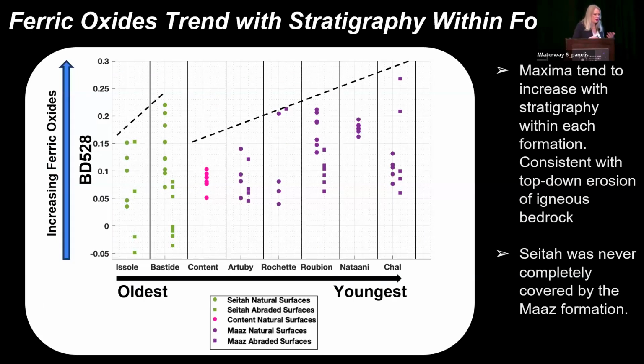So to address the exhumation histories of Jezero Crater, we plotted the BD528 value versus stratigraphy. Stratigraphy is broadly increasing from left to right. Here we see that the maxima increase with stratigraphy within each formation, and that this could be consistent with top-down oxidation of these surfaces. And this is also consistent with the fact that Seitah was never completely covered by the Maaz formation. You see that Seitah has slightly higher values than some of the lower values of Moz.